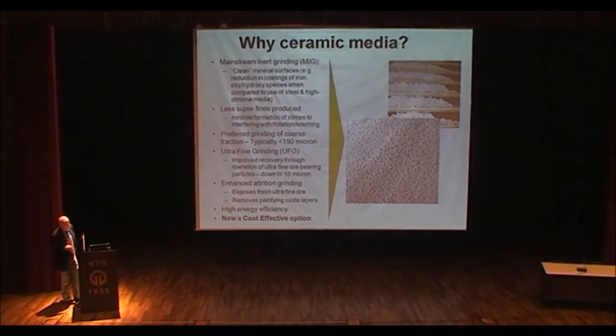And on leaching as well, I was looking through the document this morning, and Professor Habashi has mentioned it, that one of the problems in any sort of leaching is the deprivation of the leach liquor of oxygen. And one of the problems there is iron will do that. By producing these oxides or hydroxide states, it's taking oxygen out of the situation. Ceramic media is inert. If you have a rubber-lined mill or a polyurethane mill with polyurethane discs and ceramic media, you don't have this. So you have what we call mainstream inert grinding.